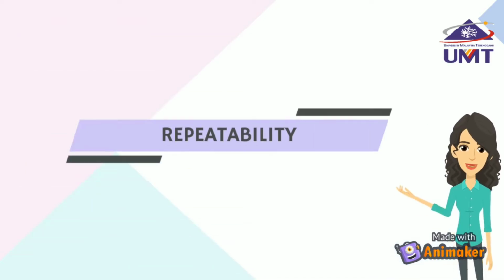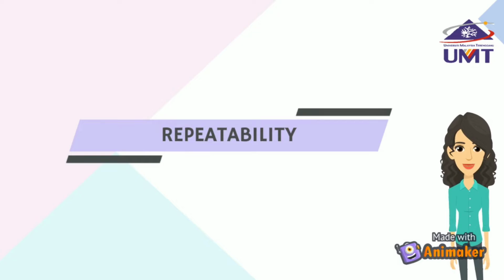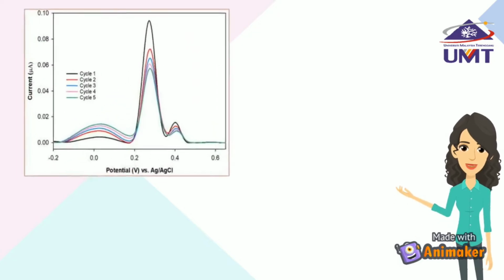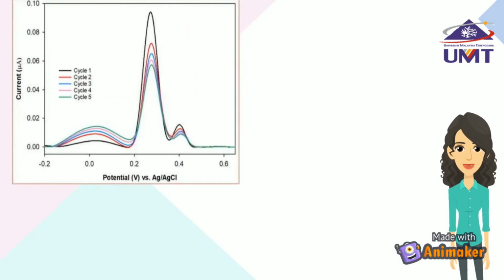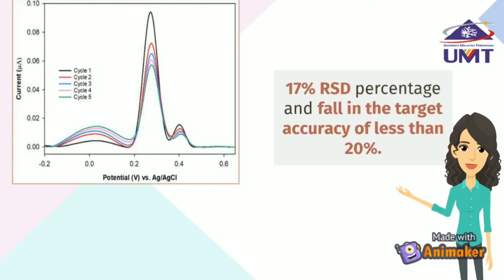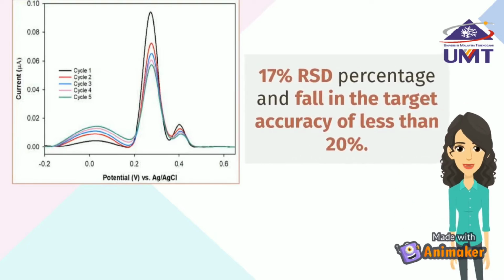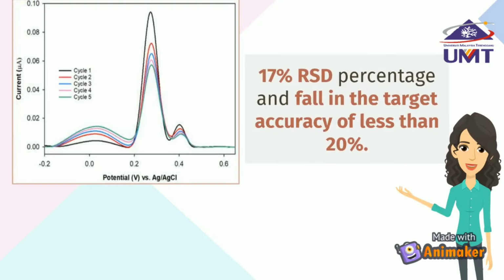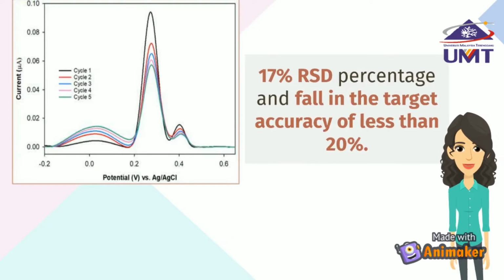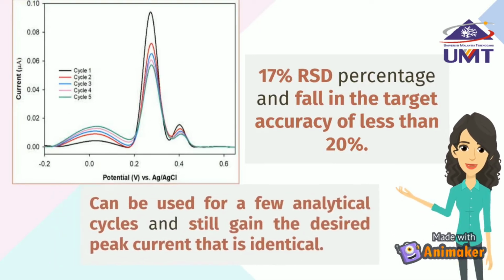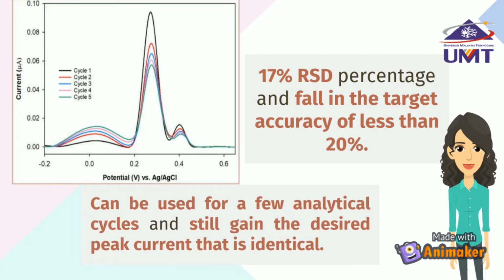The repeatability process was also done to prove the performance of the modified electrode as a highly sensitive dopamine sensor. The repeatability analysis reveals a 17% RSD, which falls within the target accuracy of less than 20%. This proves that the composite modified electrode can be used for a few analytical cycles and still gain the desired identical peak current.